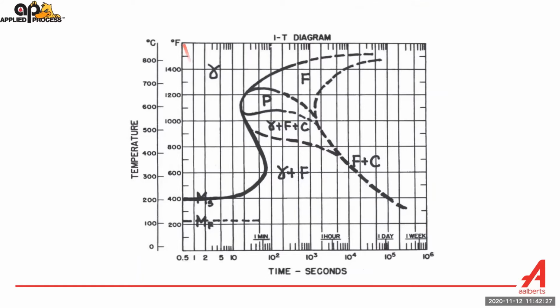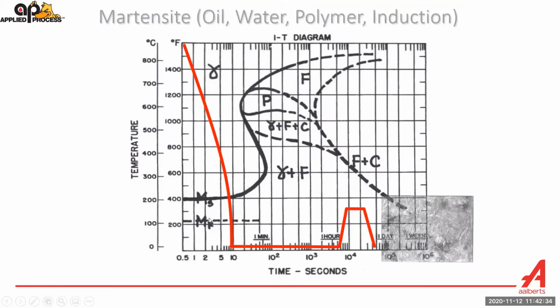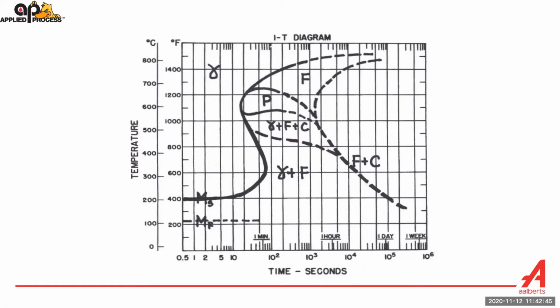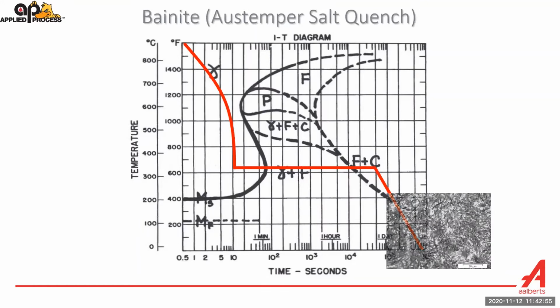So we could start at that same 1600 degrees Fahrenheit, quench the part in oil or water, and you cross these lines called martensite start and martensite finish. So you form what's called martensite, and you have to temper that. That's tempered martensite. And then there's what we do in the world of molten salt quenching. And that is you still start at 1600 degrees Fahrenheit, but because we're quenching in a molten salt bath at high temperatures, we get a different structure. And in steel, it's called bainite. And bainite has some unique mechanical properties.